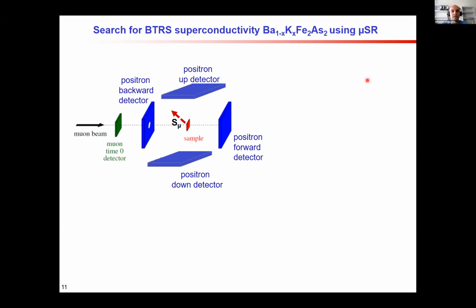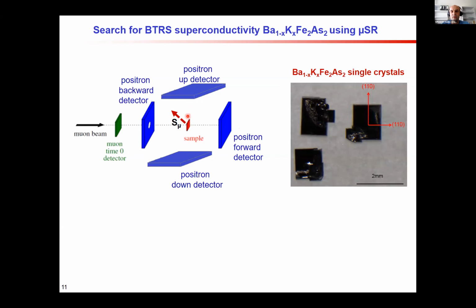So now I would like to talk a few words about our experimental setup. Here are our muons, which go to the sample, and using the two detector pairs, backward, forward, and up and down detectors, we can monitor not only the value of the relaxation rate, but also the direction of the fields in the sample.